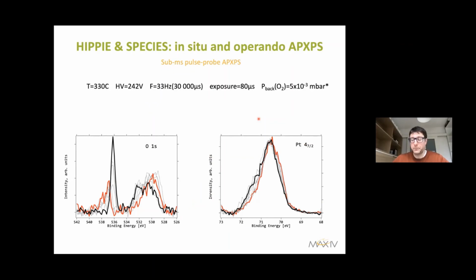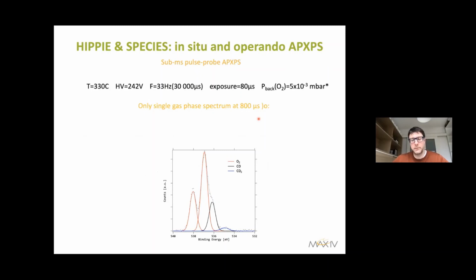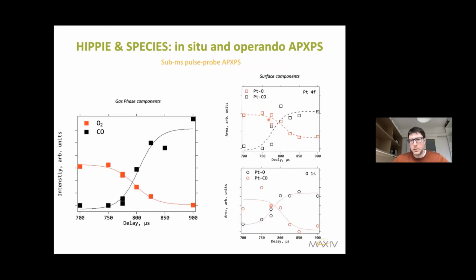with the gas phase component. For the gas phase spectra in this particular experiment, we measured only one spectrum at 800 microseconds, but it happened to be right at the top where the CO2 is mostly produced. You can see it by the ratio between CO and CO2, which happened to be 13%. So this is the correlation between surface and gas that I was talking about earlier. This is the switch between oxygen and CO phase in the gas, and this is the switch between oxygen and CO components on the surface, and you can deduce them from either platinum 4f or oxygen 1s spectra. They're pretty much the same.